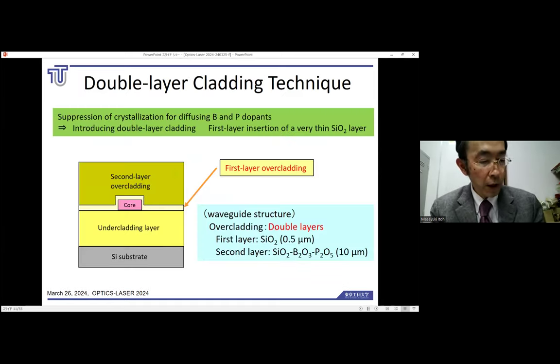One way to prevent crystallization during heat treatment is to double layer the overcladding, double layer cladding technology. Compositional analysis of the inside of the 10% delta waveguide that is crystallized as described above showed that boron and phosphorus, which are dopants of the overcladding, have penetrated into the core. It is thought that the diffusion of boron and phosphorus promotes crystallization inside. We came up with this idea.